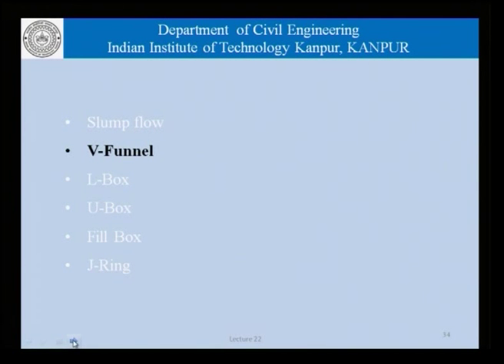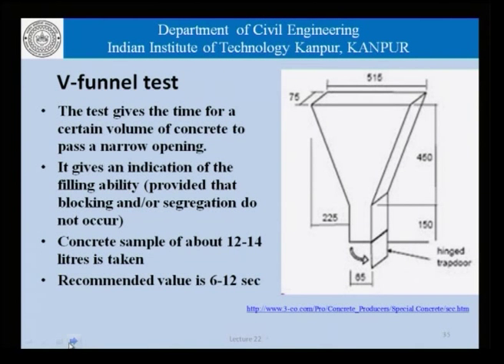Now, if we come to the V funnel test, the test gives us the time for a certain volume of concrete to pass through a narrow opening. It gives an indication of the filling ability, provided that no blocking and or segregation occur.